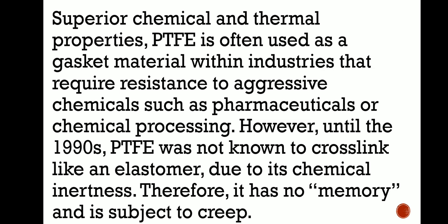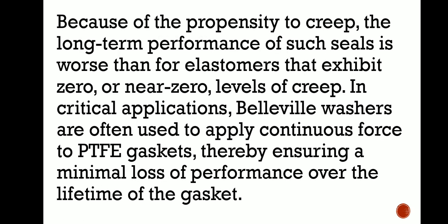However, until the 1990s, PTFE was not known to cross-link like an elastomer due to its chemical inertness. Therefore, it has no memory and is subject to creep. Because of the propensity to creep, the long-term performance of such seals is worse than for elastomers that exhibit zero or near-zero levels of creep. In critical applications, Belleville washers are often used to apply continuous force to PTFE gaskets, thereby ensuring a minimal loss of performance over the lifetime of the gasket.